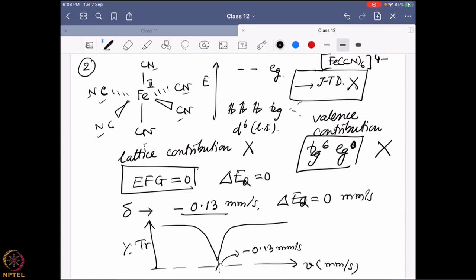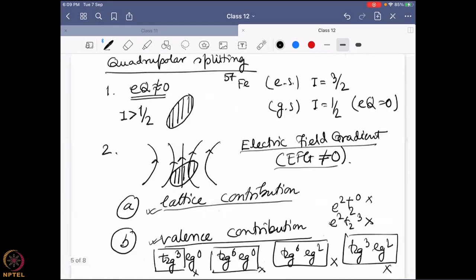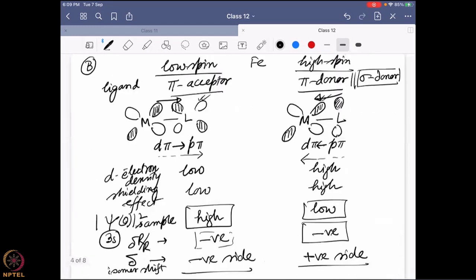Low spin means it is moving some d-electron density out. And that means it is creating more chance for the s electron density, especially the 3s electron density, to interact with the nuclei because of less shielding effect. And that is increasing the psi zero square value. And it is multiplied with delta R by R, which is a negative term. And that is why it is going to a more negative side. So this is exactly the argument we have given over there.